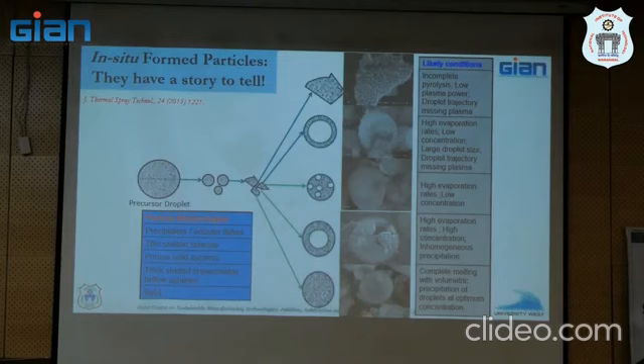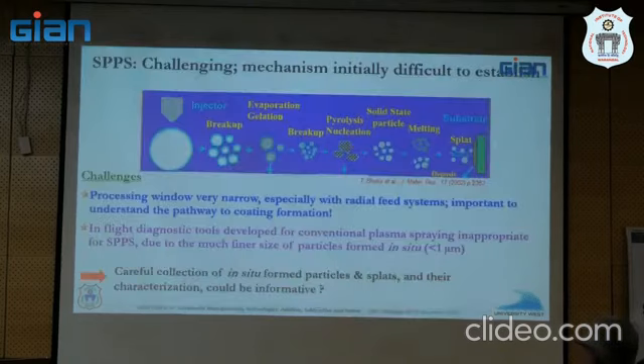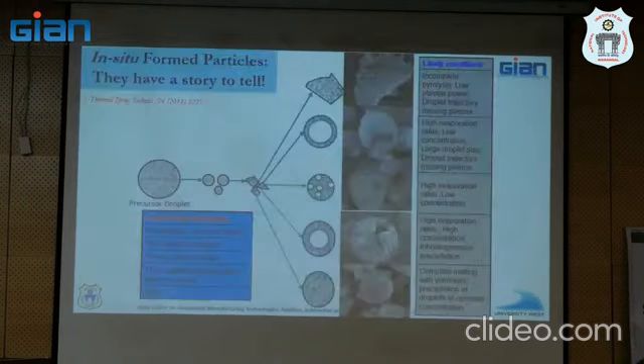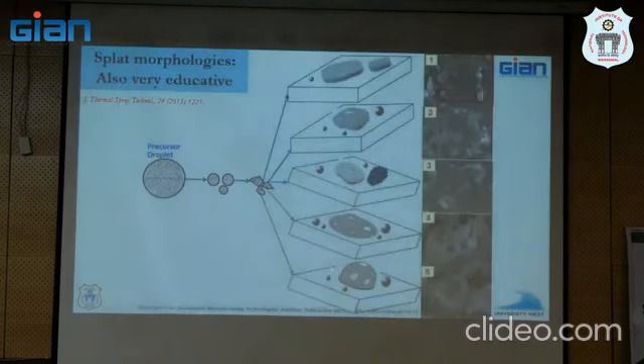So while I was at ARCI, this was work by my first PhD student, right? We have already shown that even though this may be a very complicated looking process, if you do it right, you can actually form in flight these kind of particles, which can then become feedstock for coating, right? And with some careful process evaluation, we could show that if you don't do it right, you get all lousy stuff. If you do it right, you begin to get these kind of particles, which are few hundred nanometers, but certainly sub-micron, and that is ideal, correct? That is what you want to see, right? And similarly, if you do it wrong, you get junk on the substrate, but otherwise, if the stars are aligned and you have prayed hard enough, you get nice pancakes that can lead to formation of coating, right?